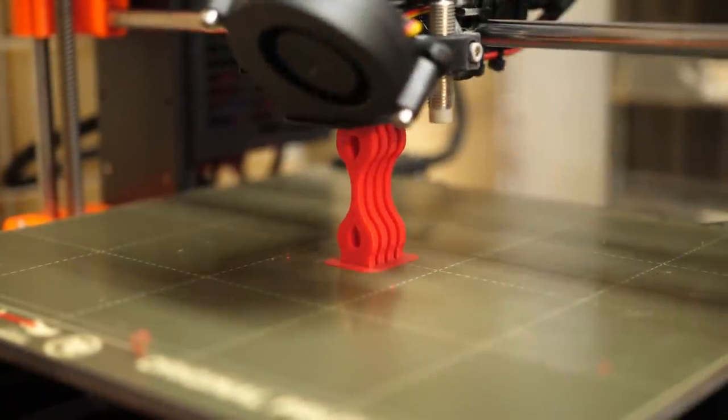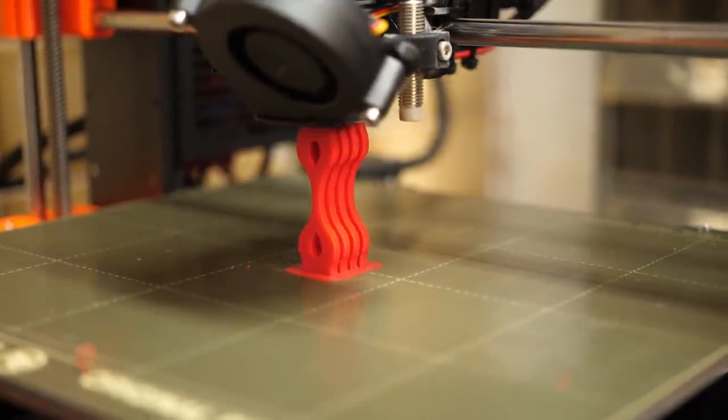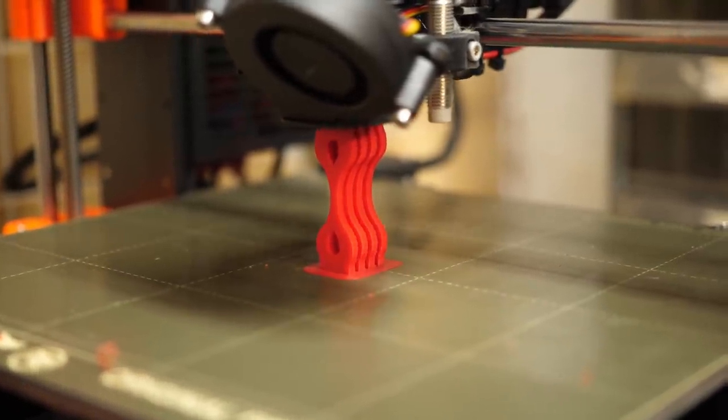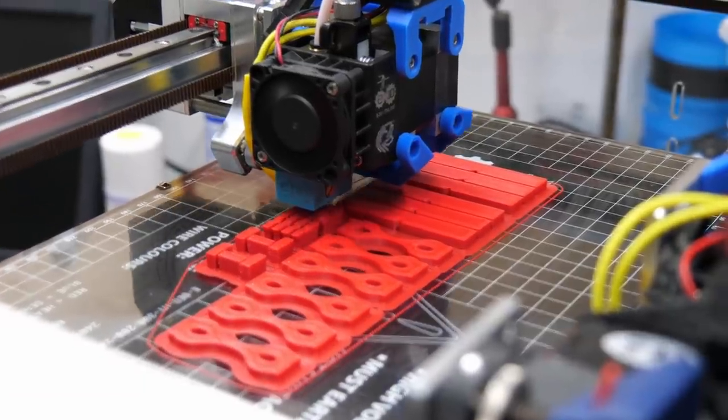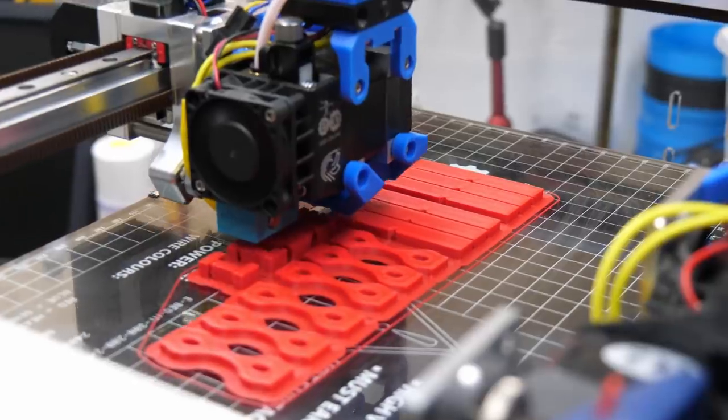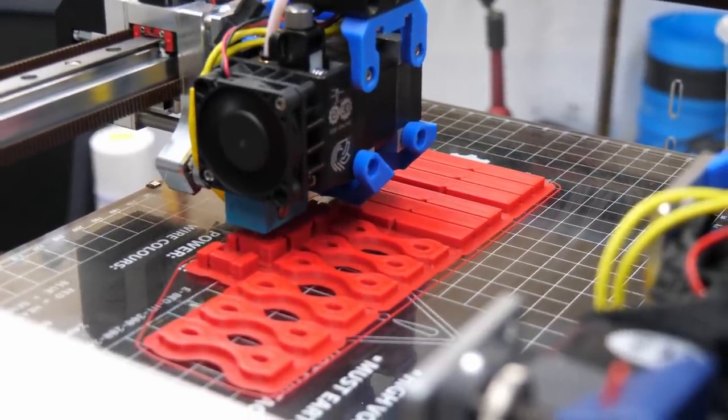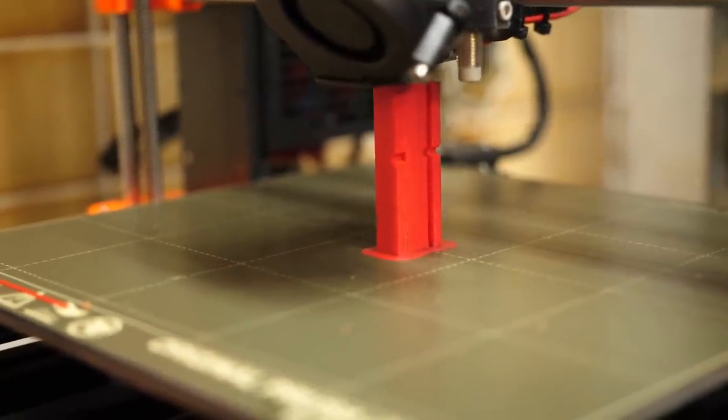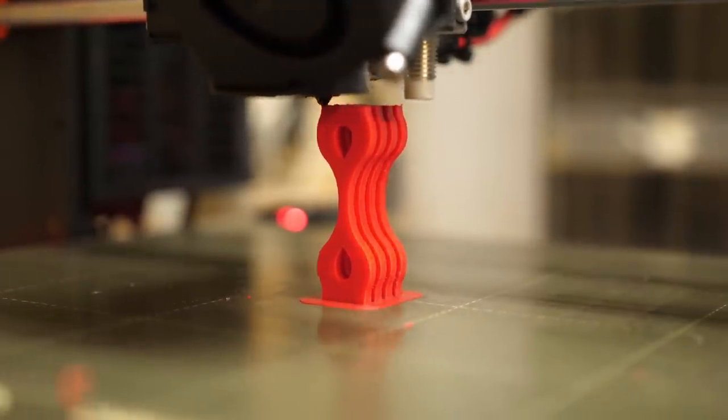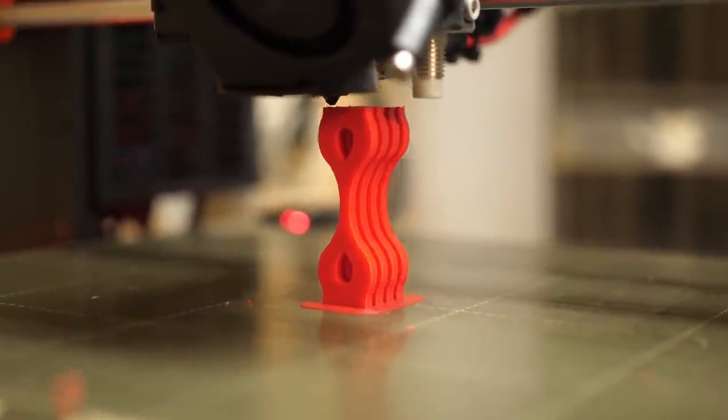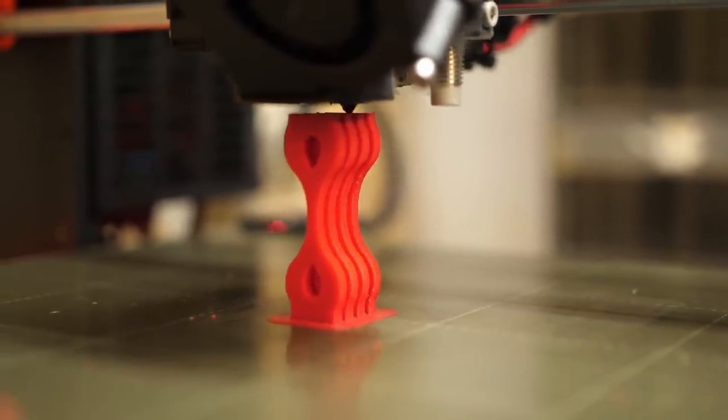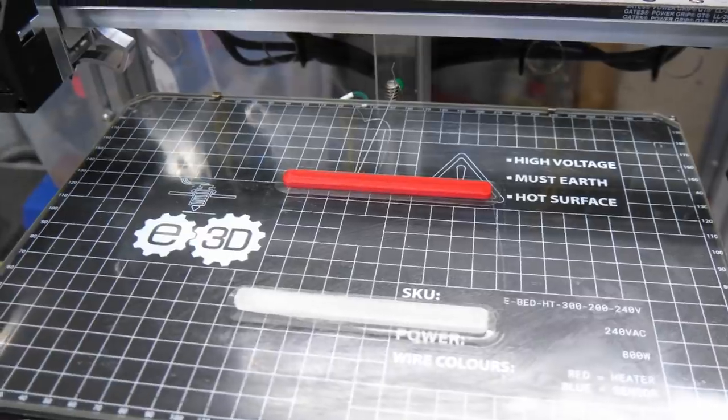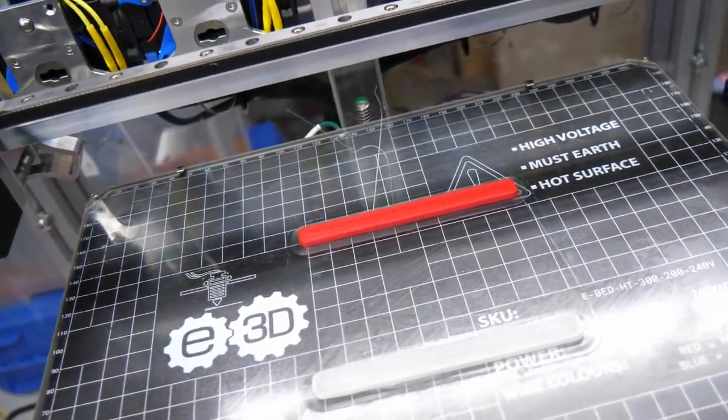Pure printing performance itself wasn't the main goal of this analysis. I wanted to find out if this material can really be annealed without the downsides of warping and increase the material properties this way. I printed a ton of samples from the base polymers as a reference and the PC Core ABS, of which I'll test one half as a reference in the as-printed state and the other half will be annealed and then tested. I manufactured impact test samples as well as my mini tensile test samples, both in the lying and more importantly in the standing orientation, where we want to see how layer adhesion changes. I also printed temperature test samples from the PC and the ABS base filaments to see when they start to severely soften to choose an annealing temperature for the following tests.